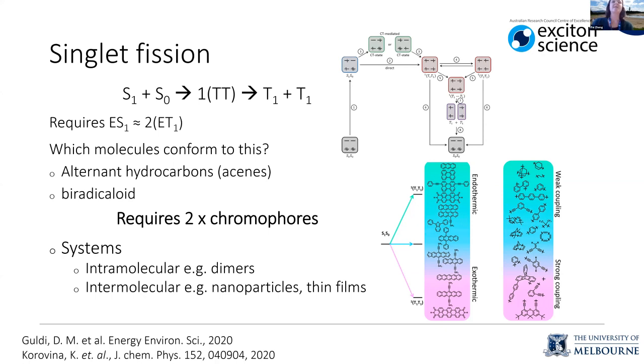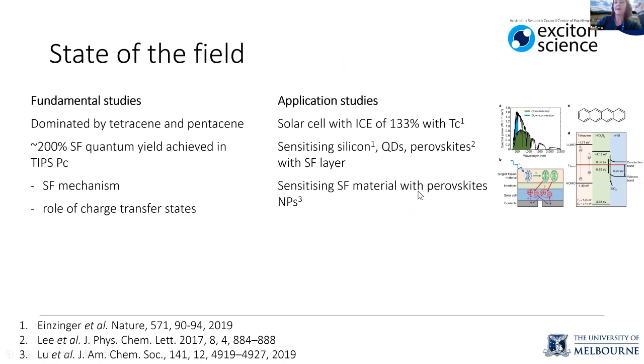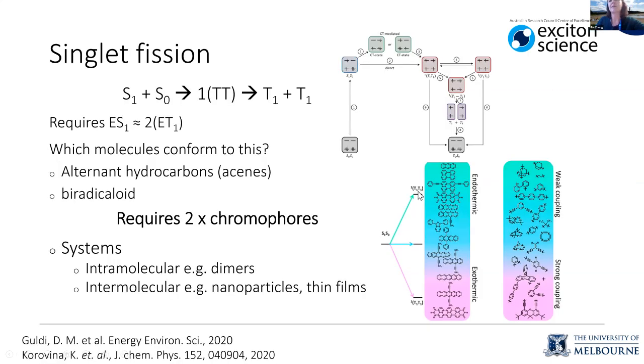And so you can imagine that the absolute smallest system that you can study would be a dimer of these two chromophores. Or you could look at intermolecular singlet fission in things like nanoparticles and thin films. Yeah. So this schematic here is pretty nice. It's just showing you that there are some systems where twice the triplet energy is higher than the correlated state. There are some systems where it's roughly equal to, and there are some where it's lower. So it means that you can have endothermic or exothermic singlet fission.